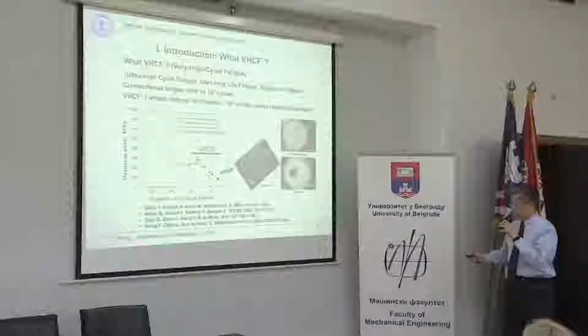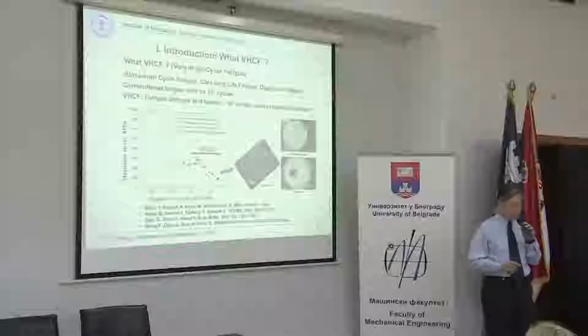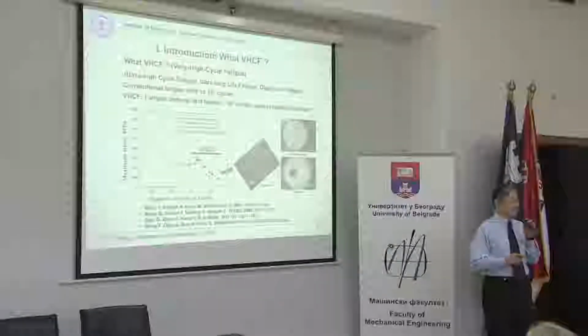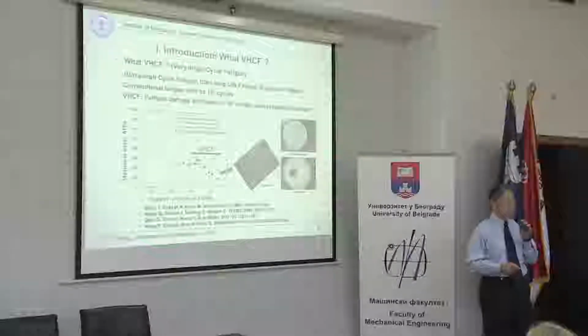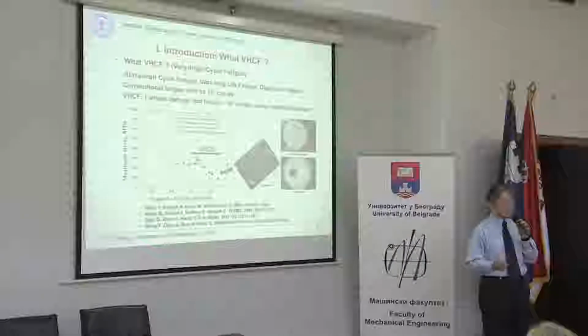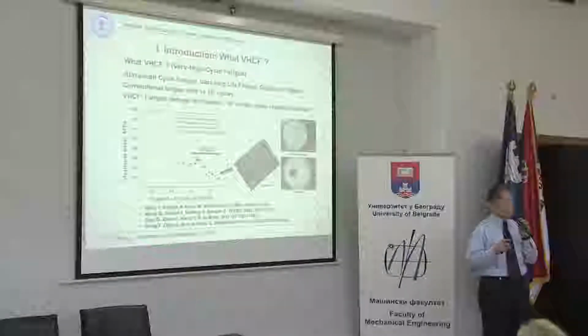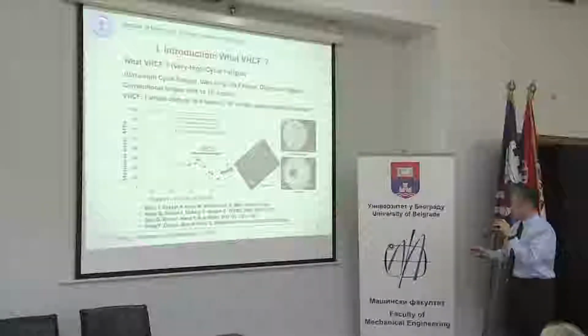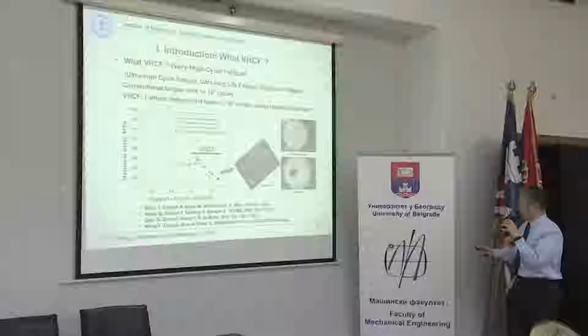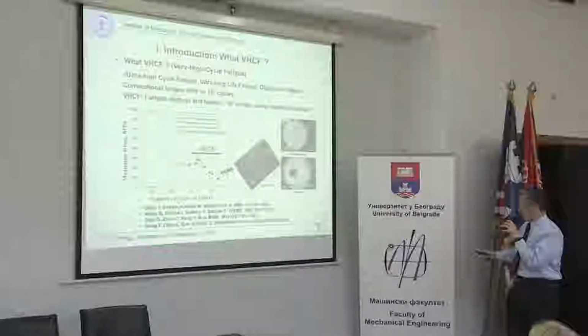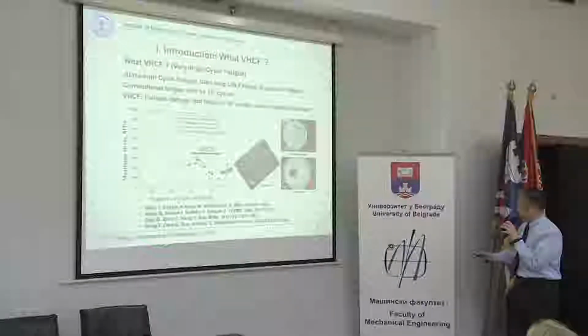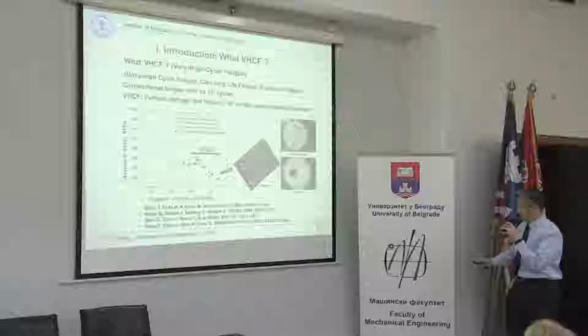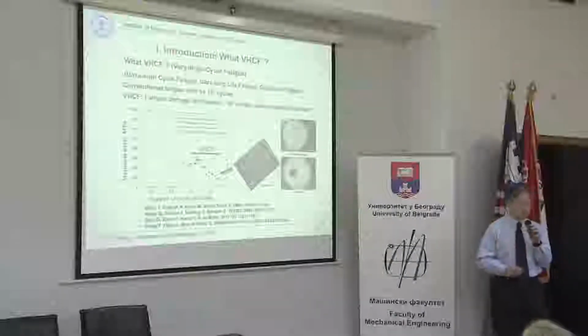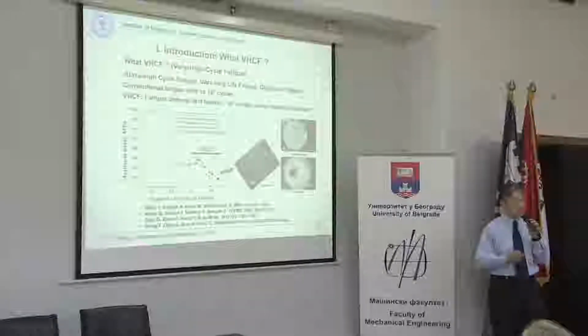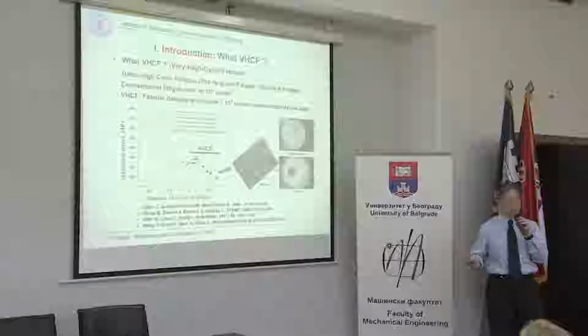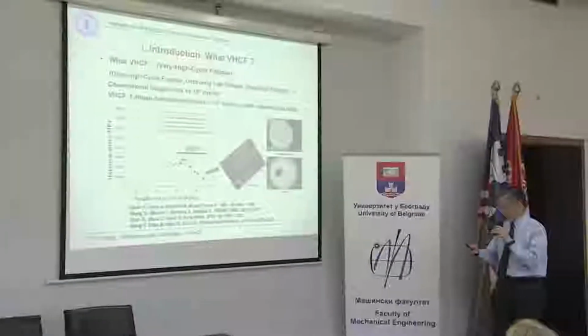And this is an example showing the major importance of very high cycle fatigue. Fatigue crack initiation is almost always from the inside, from the interior of the material, the specimen. This example shows a cross-section of the specimen and the point of initiation, and the enlargement shows this type of morphology, and an even greater enlargement shows the detailed feature of this initiation spot. And I will go into detail about this feature, this phenomenon.